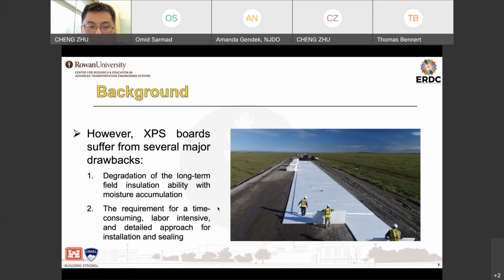The reason is that XPS boards suffer from several major drawbacks. Two typical ones: first, the degradation of the long-term field insulation ability with moisture accumulation in the XPS boards. And second, from the figure, you can see that it takes a significant amount of labor and time to install those XPS boards in the field, because all the boards need to be well aligned with all the joints sealed. So it is labor intensive.